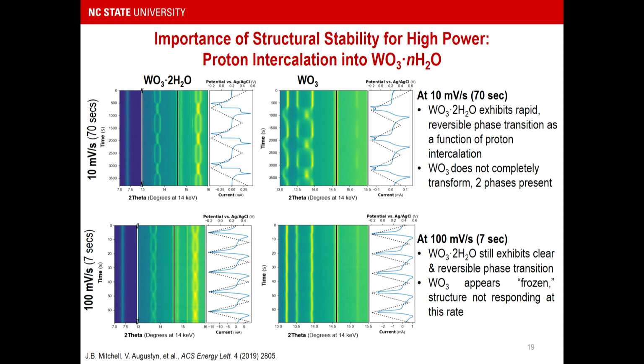And these are some of the fastest operando X-ray diffraction experiments for energy storage devices, I believe, that are out there. And we find that what's likely happening in these materials is that the water is limiting the structural degrees of freedom that can be possible as protons intercalate, and that this essentially stabilizes the structure, fixes it, and makes it respond incredibly quickly.